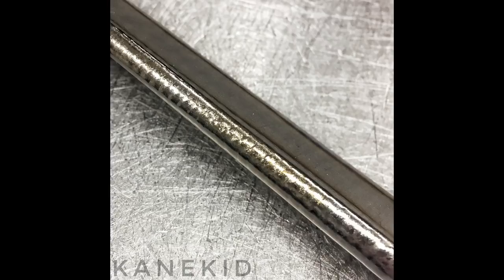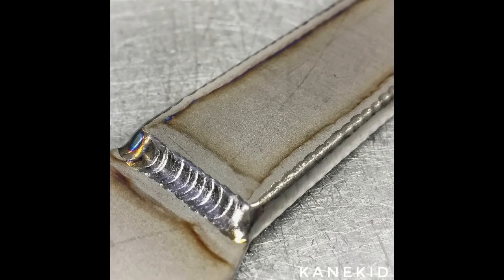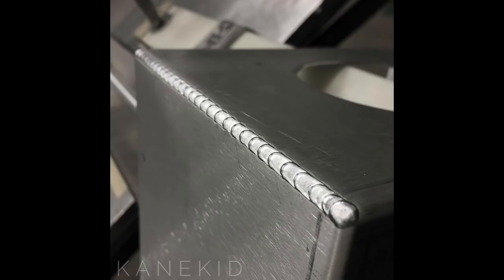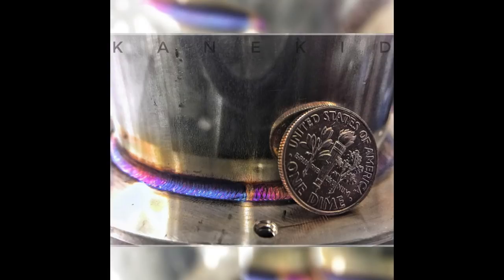So on aluminum, typically a raw rolled sheet of aluminum has that surface oxide on it. Depending on how deep, you can see that goldish tinge on aluminum. You don't really notice it until you brush it off, and then it goes from a blue metal to a yellow metal, on the extreme side of things. So typically I just wire brush that off and then wipe it with acetone, or it gets run through a sander. If it's not an old sheet of aluminum, and it's not too bad, we'll just remove it good enough.